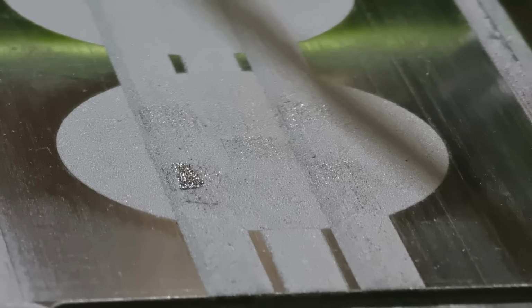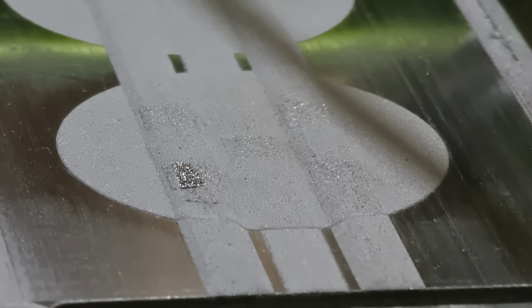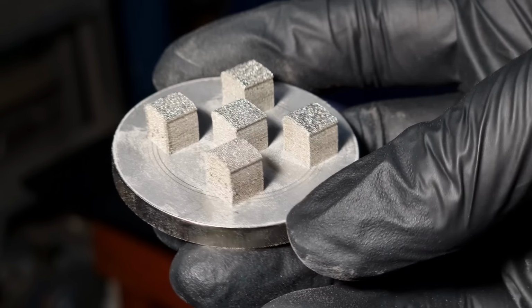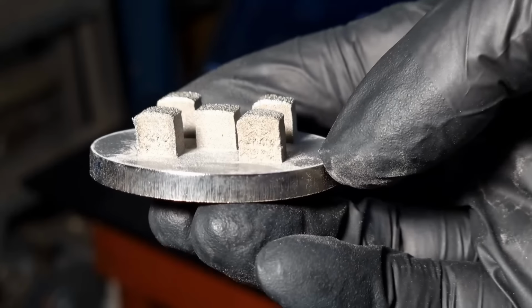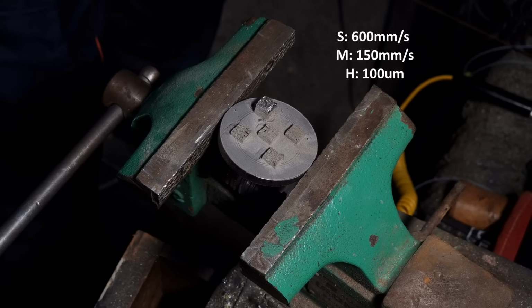I tried again, but this time performed a multi-pass scan attempting to eliminate most of the spatter by performing a sintering step followed by a melting step. Watching the footage I couldn't see much in the way of spatter, which was a win, but it appeared that the unevenness still remained. The additional heat from the multi-pass approach was also having an adverse effect on the recoater blade, particularly for the cubes aligned in a row, hence why they are shaped like loaves of bread. This would no doubt compromise the results, but at least one of them managed to survive me wrenching on it.